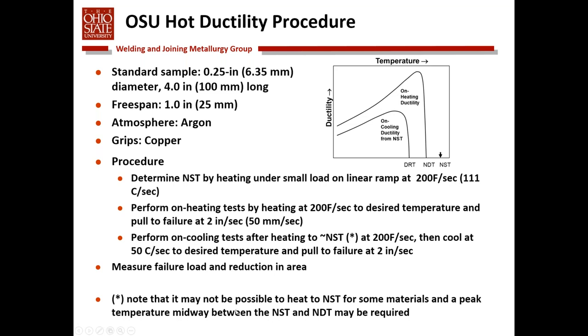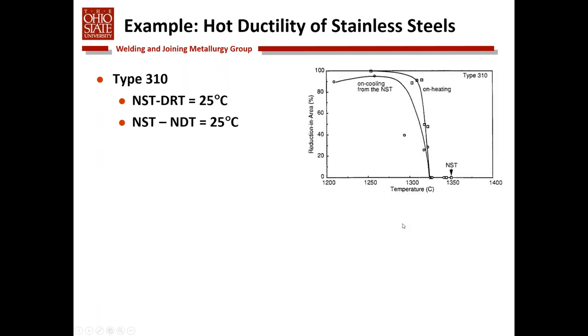One notation here is that in some materials, it may not be possible to heat all the way to the nil strength temperature without the sample coming apart via melting. And so a temperature midway between nil strength and NDT may be required. This is certainly true for a lot of nickel-based materials. So here's an example of some hot ductility data for stainless steels. This is type 310. We see our nil strength temperature. We see that the NDT and the NST are almost right on top of each other. And so this differential between NST and DRT is only about 25 degrees centigrade.